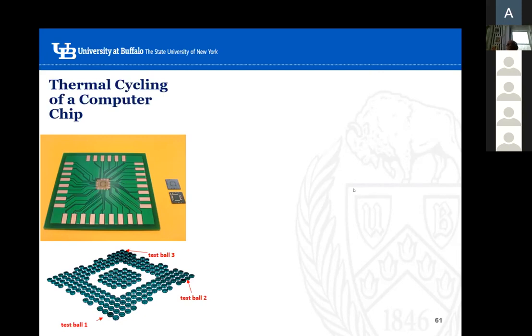But the first constant, K into delta epsilon P power alpha, the first number K is nothing but 50% of the ductility, delta epsilon F divided by 2. So basically it says that if in one half cycle it can fail by the loss of ductility, suppose N equals 1, if you put one cycle, it has to fail. Naturally, K should be delta epsilon F by 2 only.